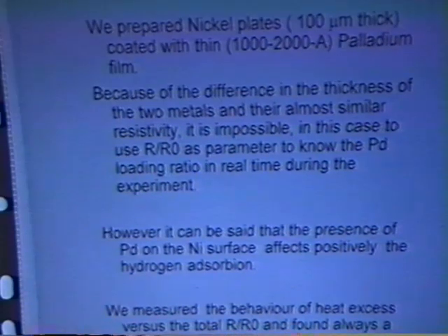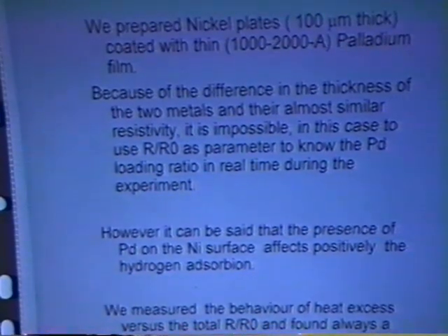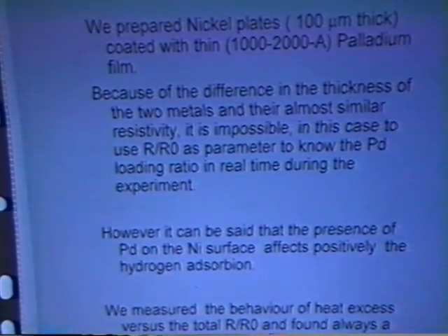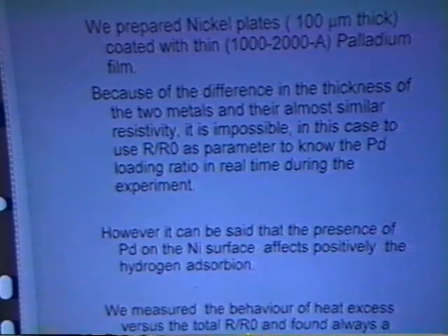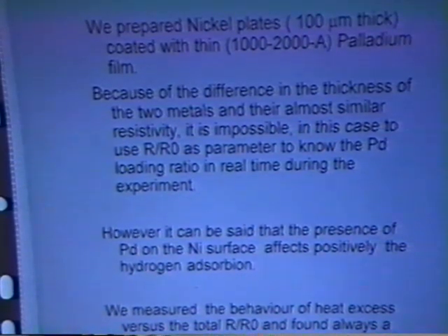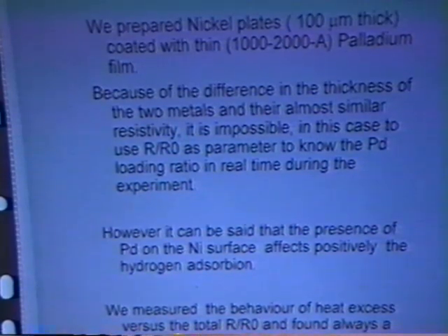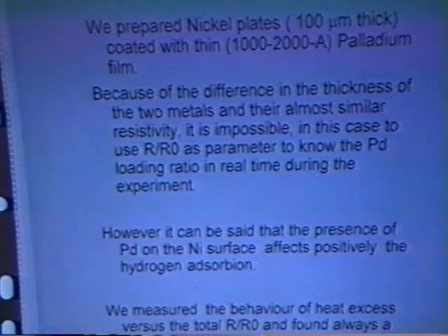We prepared nickel plates, 100 micron thick, coated with palladium. The palladium film was obtained by thermal evaporation without particular care in cleaning the surface of the nickel, I mean without pre-patterning or chemical etching.